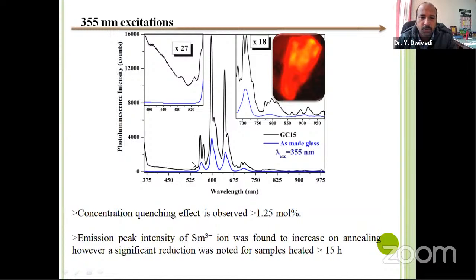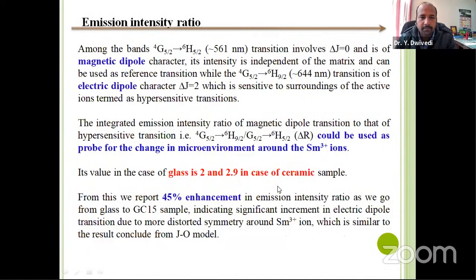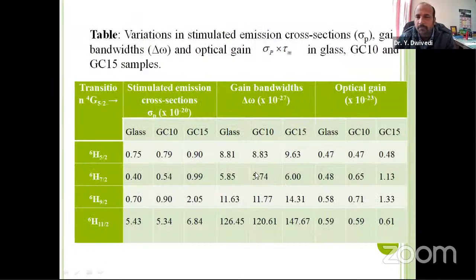So if you take a ratio of these two, you get some idea about how the microenvironment around the lanthanide ion is changing. In case of glass ceramic, we find it is around 2.9 in comparison to glass, which is around 45% enhancement. This matches with the result we concluded in the case of the Judd-Ofelt theory.